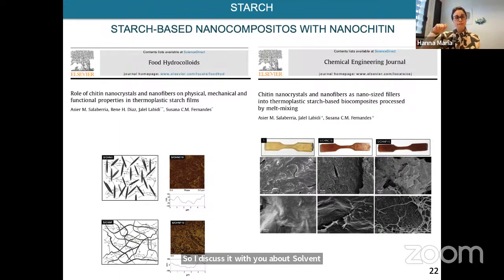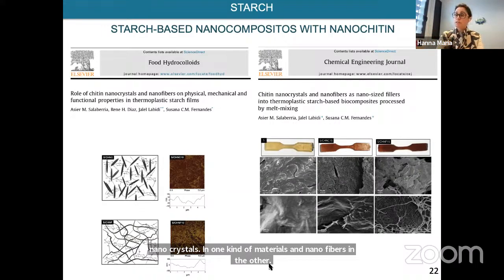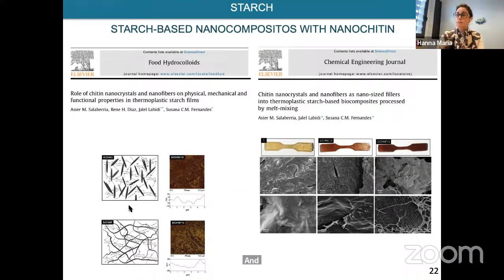So we first dissolved the starch in water at 90 degrees. And then we incorporated different forms of chitin, nanocrystals in one kind of material and nanofibers in the other. And then we just let the solvent, that was water, evaporate.